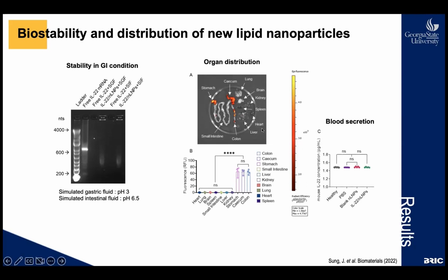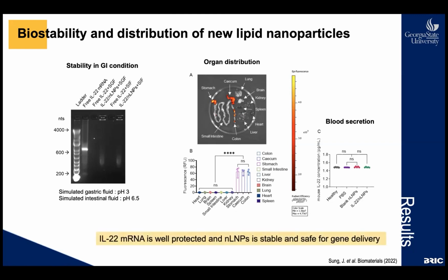To check the secretion of IL-22 in the circulating system, we checked the IL-22 concentration in the serum as well, but no difference between the groups was measured. All this characterization of the drug delivery system proves that IL-22 mRNA is well protected and the lipid nanoparticle is stable and safe enough to test in vitro and in vivo models.